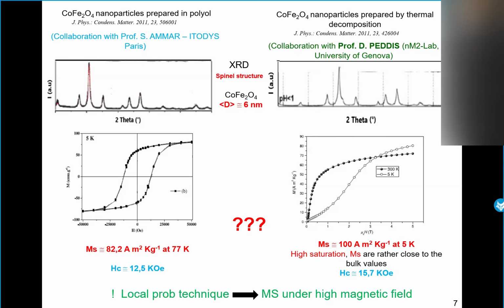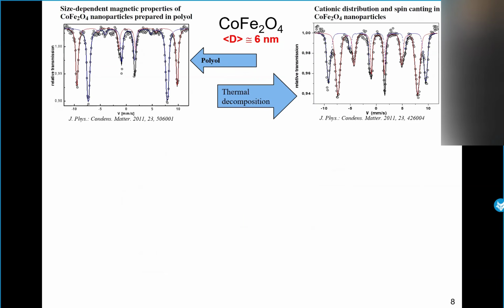We performed the measurement under external applied field, and we obtained these two spectra. The first one is a classical spectrum under field. We observe a splitting between the two subspectra for A and B with narrow lines and with very small intensity for the intermediate lines, which shows very small spin canting.